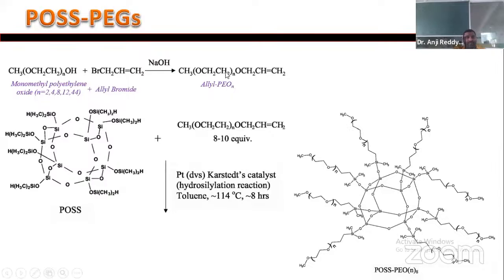And this allyl PEO reacts with the POSS. This is the POSS. That POSS reacts with this allyl PEO, and we get the POSS-PEOs. If we add this POSS-PEO as a plasticizer at low chain lengths, it increases the conductivity and the mechanical property very well. That increases both.